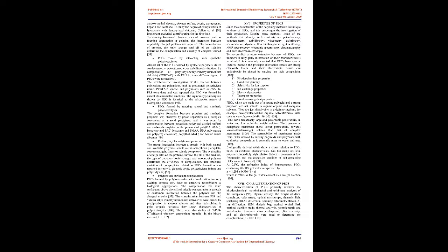Amorphous natured multi-layers can be blended with charged substances, for example, drugs and proteins. Perez-Anes 67 effectively united chitosan and poly-β-cyclodextrin over the surface of titanium and loaded with gentamicin to aim at perioperative infections by LBL aggregation. The benefit of the LBL technique is that the obtained PECs are stable and the utilization of the layers involves coating matters. 68. This procedure is slow and a smooth surface is required for the aggregation of the following polymer layer. 65, 68.